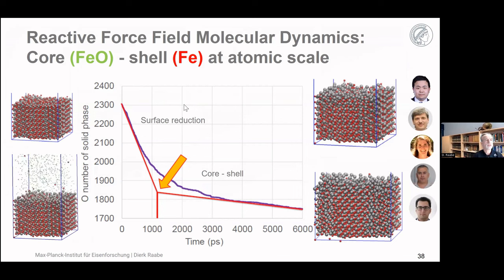And you see that also in this MD simulation, you have a transition from a surface reaction to a core-shell, to a sluggish core-shell structure when the first iron layer has formed in the simulation. Yet the thermodynamic fidelity of these potentials is very poor. If you use these potentials to calculate points on the phase diagrams, they're often really pretty wrong. So they kind of look right, but the scientific depth of some of these simulations is still pretty shallow.